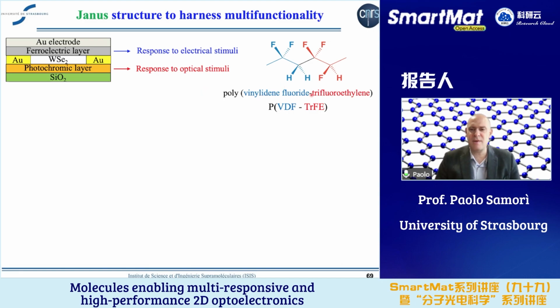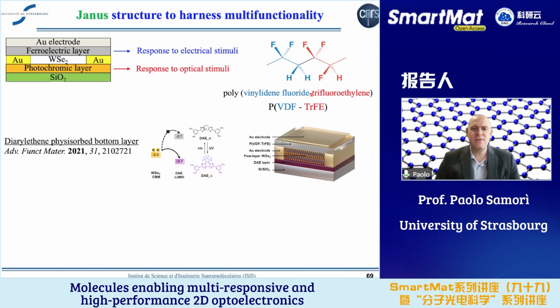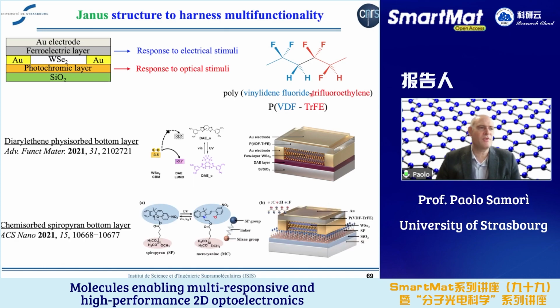And so also this approach is non-volatile. And so you can see that we have reported two approaches in two different papers. The bottom photochromic layer can be either a diarylethene layer, like the one we showed so far, or it can be a self-assembled chemisorbed spiropyran layer that you see here, with a silane unit to chemisorb on the basal plane of silicon dioxide. And then we have tungsten diselenide, and on the top we put the same ferroelectric layer.